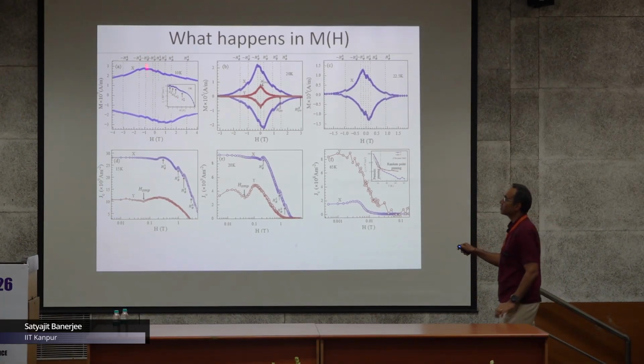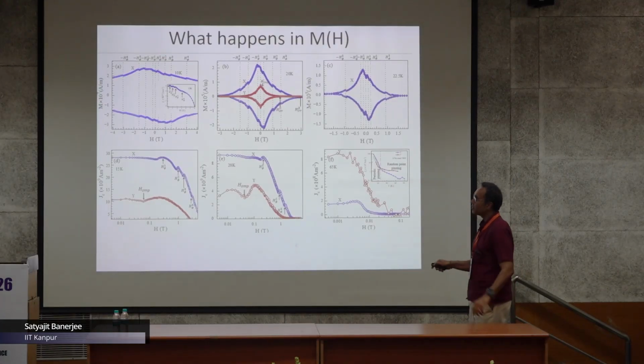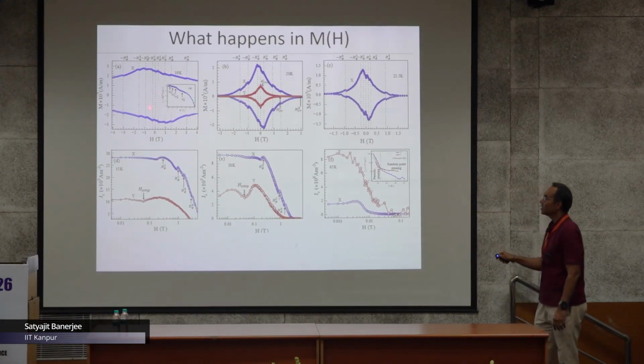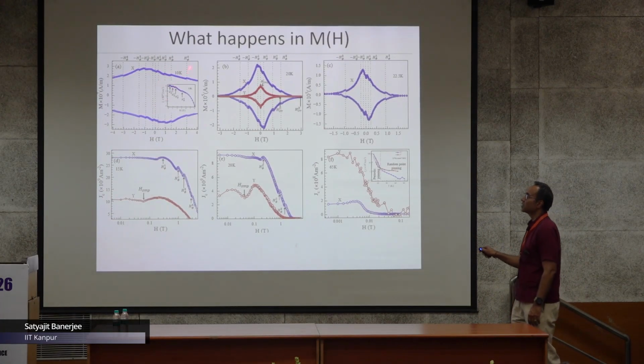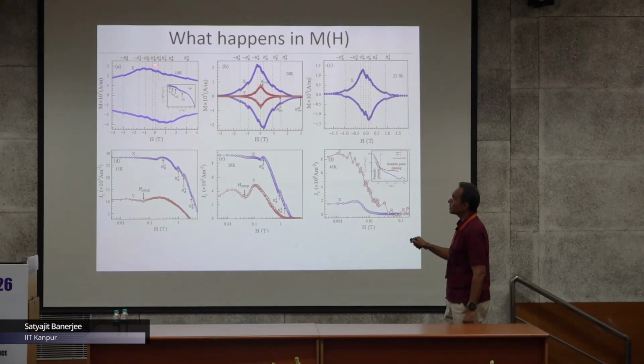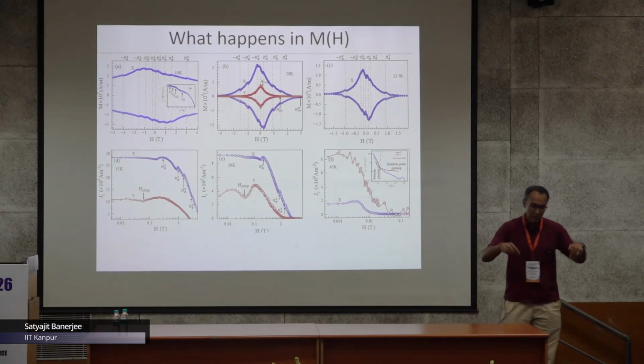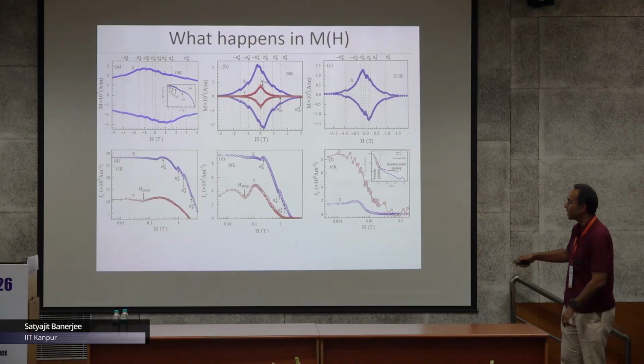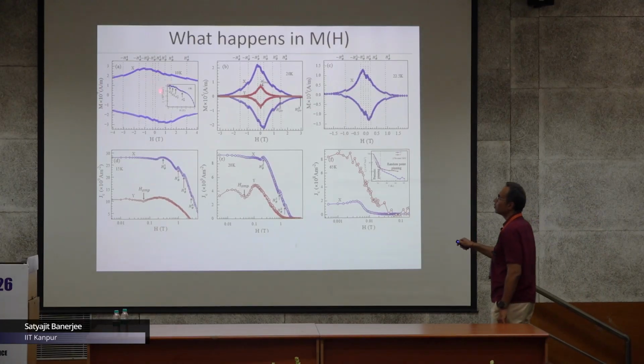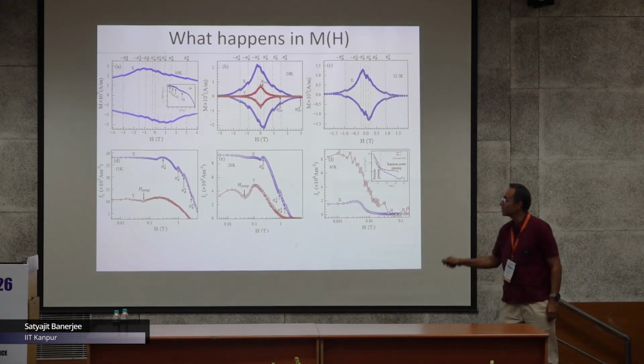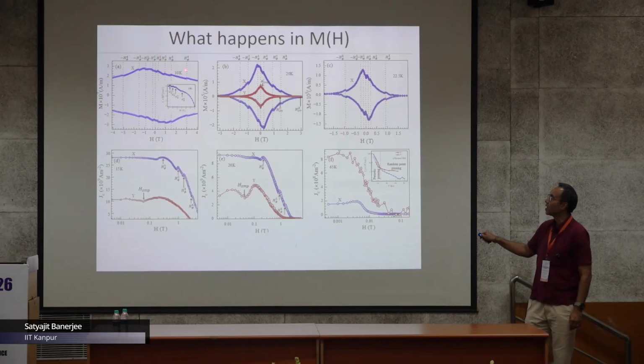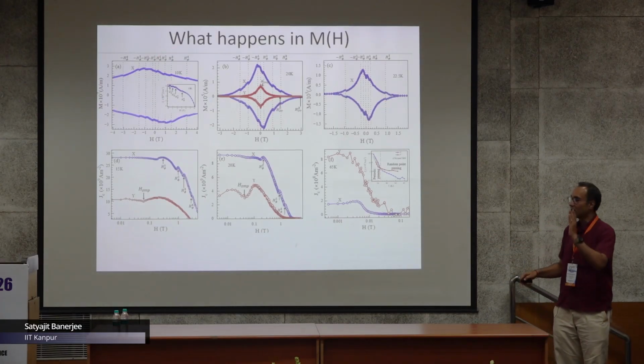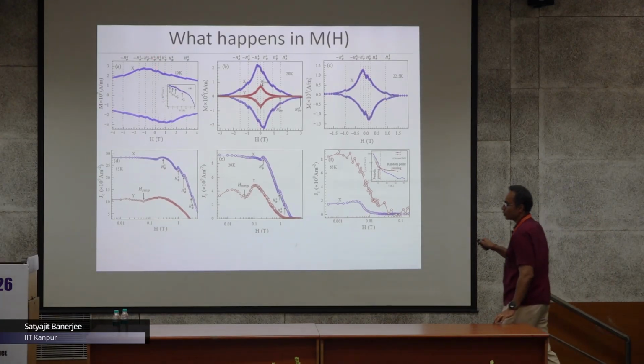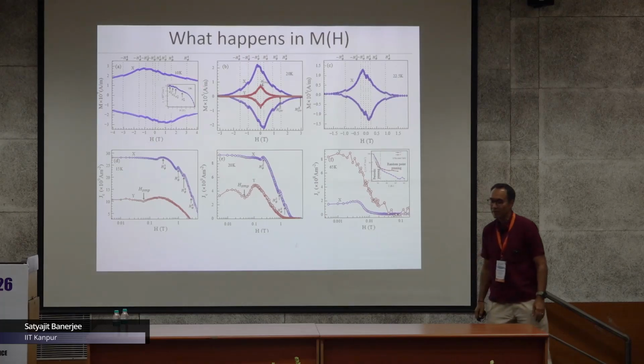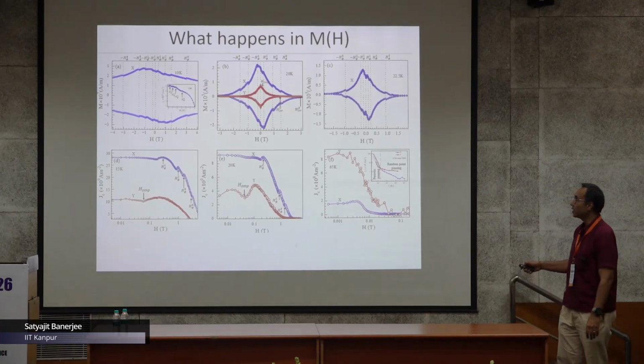These are superconductors with no artificial patterning, but there are intrinsic modulations present. Whenever the vortex state matches with some periodic pinning inside the system, you get a step in magnetization, and these magnetization steps occur at very fixed magnetic field values that you can pick up regularly.